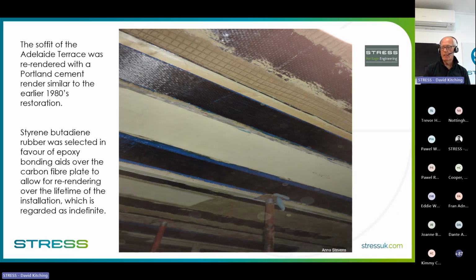Guess what? It was sand and cement. So that render that had been put on, we don't know when, I think about 30 years ago, was actually sand and cement. It wouldn't have been that in the first place. It would have been lime render, but for some reason they'd managed to get sand and cement on it. And so we had to match that. We were, however, allowed to put in some SBR, which is a sort of an additive that makes the sand cement more sticky, and slightly more pliable, so it bonds better and will last much longer.